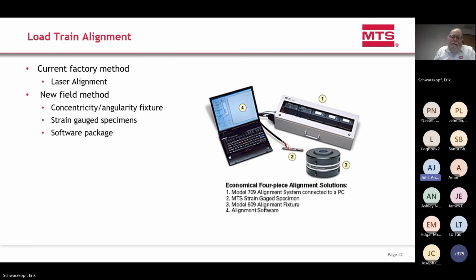Most modern machines, fatigue machines, have some kind of tool to adjust the alignment to minimize the misalignment. And most of them use a strain gauge specimen to verify that misalignment has been adjusted out of those grips, that the grips are now concentric and with a parallel angularity to each other.